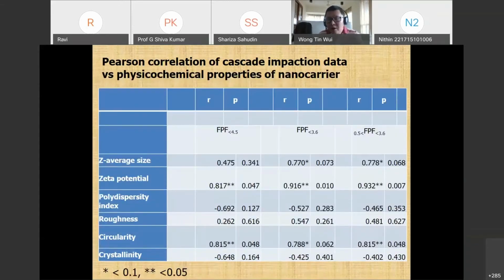Now, after blending the microscale particles with the chitosan nanoparticles at a specific ratio, we move forward to conduct a cascade impaction study to simulate the aerosolization and inhalation process of the nanoparticles. From this exercise, we realized that the size, zeta potential, as well as the circularity of the nanoparticles dictate the inhalation efficiency of the drugs.